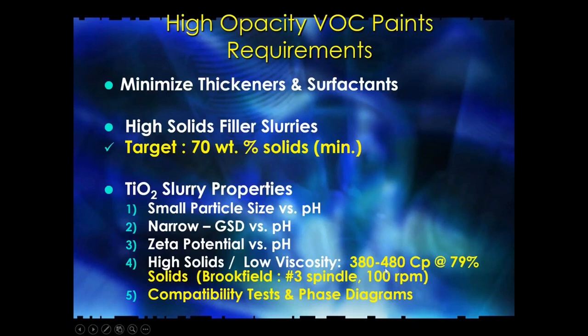They were able to throw out the resin supplier. They were able to look at the titanium dioxide supplier. And fortunately, company B, who had the gold standard, did something wonderful. They changed the way they put the alumina down on the surface. They came from the acid side, whereas everybody's coming from the alkaline side. And they did an excellent job of giving a surface which was amenable to dispersing with the hydrophobic co-dispersant.